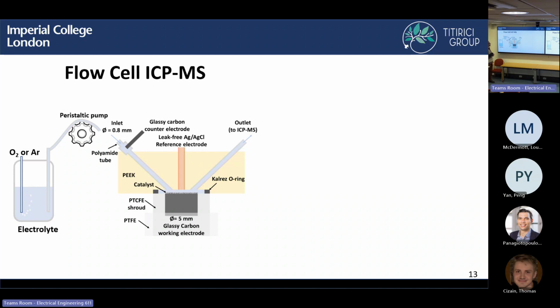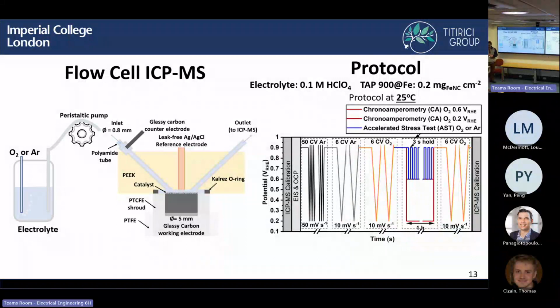So what we did first is conduct measurements with this flow cell ICP-MS. So in this configuration, you have your electrolyte, which is being pumped through this flow cell, and you have either, say, argon or oxygen dissolved in that electrolyte, and that's going towards your catalyst layer and then goes straight through to your ICP-MS. So with this method, you're just dissolving your inert gas or your active gas into the electrolyte. And this, unfortunately, for oxygen, which is our reacting species, really limits the current density, which we'll see in the next slide. But still, it is interesting for a model system study to really understand what can happen. And so this is the protocol that we used.